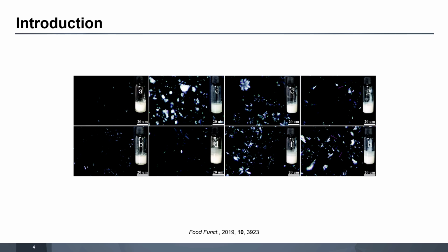Despite its contribution to skin barrier function, ceramide has some problems to be incorporated into cosmetic formulations. Due to their hydrophobic tails, they have a strong tendency to phase separate or form molecular crystals, which seriously hinders diversifying their formulations. After preparation for formulation, there is the precipitation of crystalline particles. Thus, viscosity also increases by gelling, making it difficult to apply for cosmetic formulations.